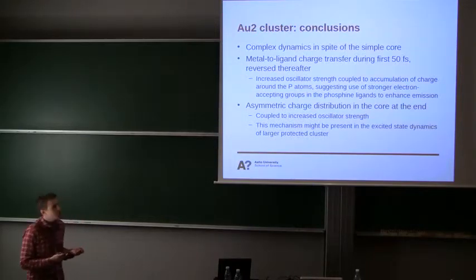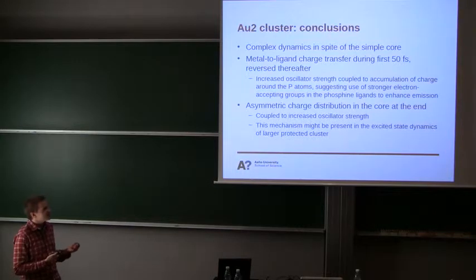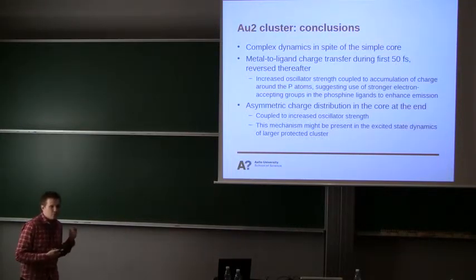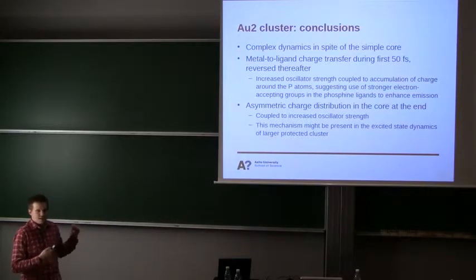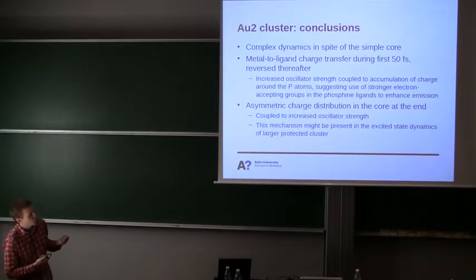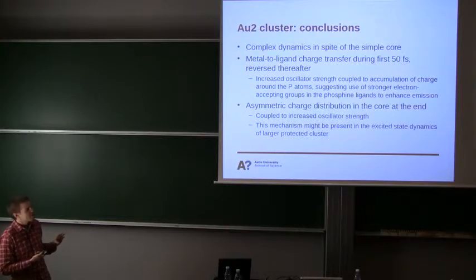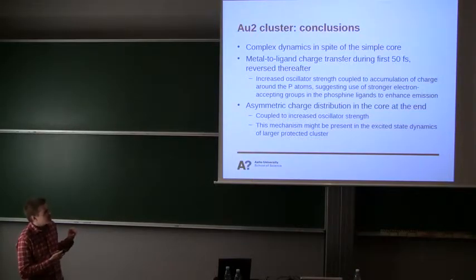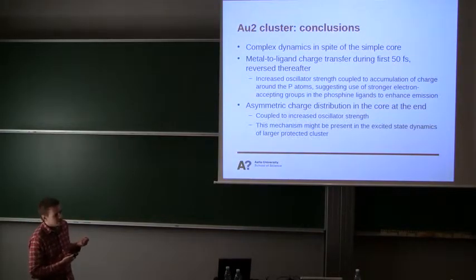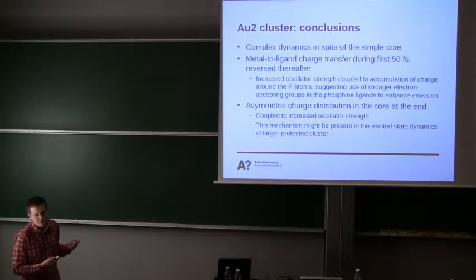The other conclusion is the asymmetric charge at the end. We could suggest that this kind of mechanism coupled to increased oscillator strength might explain some luminescence properties in the case of larger core clusters, which we cannot study with real-space Ehrenfest studies. For example, we know that the luminescence is enhanced when some dyes are attached to gold clusters, and this asymmetric charge observed here might be related to that.